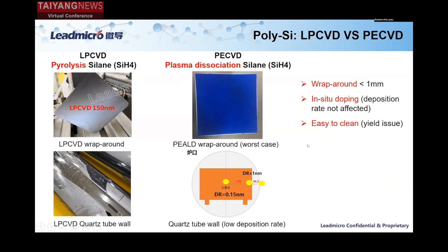We will share more later. The second thing is the operation cost. You can see the bottom graph here, on the right side. We all know the tube type PECVD system is based on the direct plasma principle. So only in the yellow color you see here, the graphite boat area, we have a very high intensity of plasma, which gives a high deposition rate. However, at the quartz wall area, the plasma density is very low, and as a result, the deposition rate is also very low. Our system has been in the field for more than 3 years and close to 1 year of mass production already. We never encountered a problem of replacing the quartz wall tube due to deposition. So this perfectly resolves the bottleneck faced by the LPCVD method.